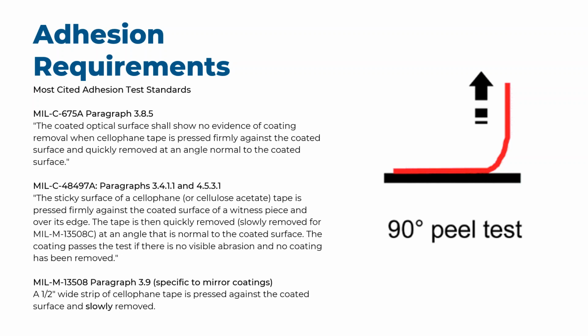So with adhesion requirements, this is almost always a cellulose tape test. Cellulose tape test, it's your Scotch 3M tape. MIL-C-675 came out in the late 60s, early 70s. It's a very rudimentary specification. You're basically putting cellulose tape down on your coated surface, you're rubbing, and you're pulling it away. Now you get into the subjectivity of the specification. Am I pulling this away quickly? Am I pulling this away slowly? At what angle am I pulling this away at? And how tightly do I have to put the tape down on the surface? That's really some of the subjectivity of the specifications and how you maneuver through them.